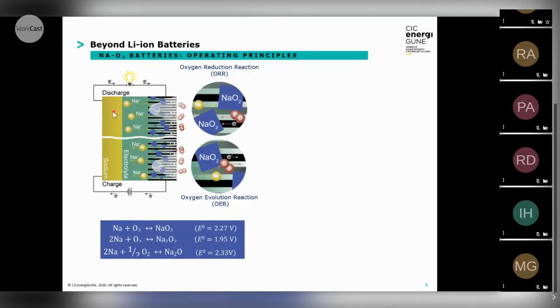During discharge, what happens is the sodium is oxidized, migrates to the cathode, and at the same time at the cathode, the oxygen reduction reaction occurs, where the oxygen is reduced and then combined with sodium to potentially form all these kinds of sodium oxides. And in principle, this reaction is reversible upon charge. So the main difference is that energy is stored in this discharge product.